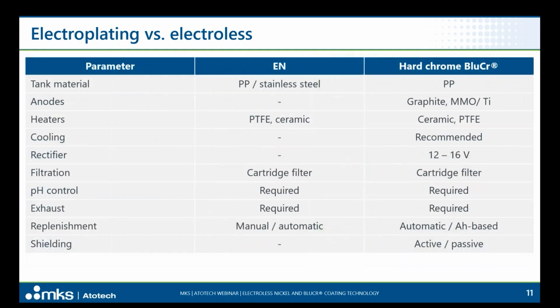Regarding the equipment, what do we need for these two technologies in comparison? We can see that in case of electroless nickel, we don't need anodes, we don't need cooling rectifier, we don't need shielding. But for both technologies, we need to do a replenishment. In case of electroless nickel, this replenishment can be done automatically or manually. In case of hard chrome, BluCr, we need to do an automatic replenishment. We need to have an exhaustion as well to eliminate the toxic aerosols in the air. We need to have a very accurate pH control in both cases. We need to filter our solution to remove the impurities. And also as heaters, we can use the same heaters, PTFE or ceramic, and the tanks are also similar.